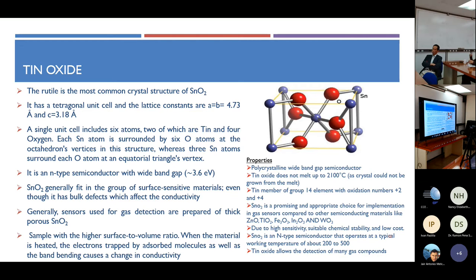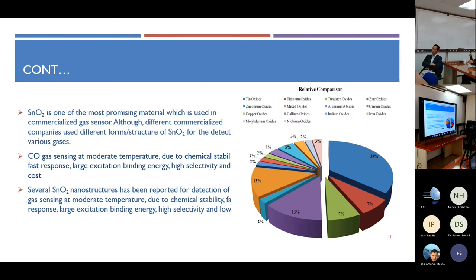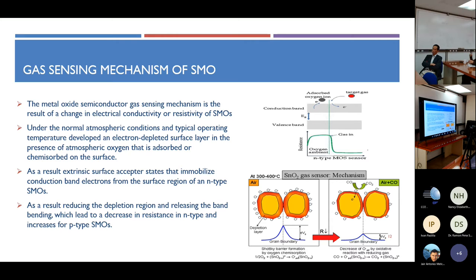Generally, sensors used for gas detection are prepared from thick porous tin oxide samples with a higher surface to volume ratio. When the material is heated, electrons are trapped by the adsorbed molecules and band bending causes a change in conductivity. It is a good property for tin oxide. The literature survey shows that among all the metal oxide semiconductors, tin oxide is the most successful gas sensor, with moderate temperature, chemical stability, fast response, large exciton binding energy, high selectivity and low cost. This is the literature survey I have done.